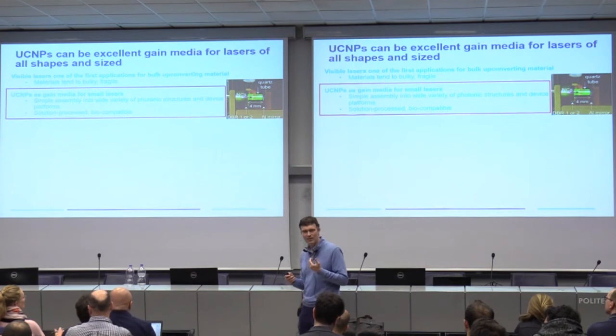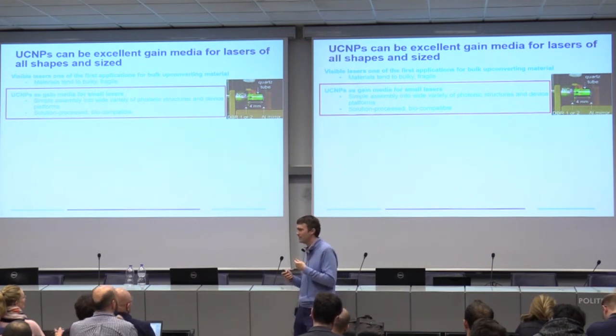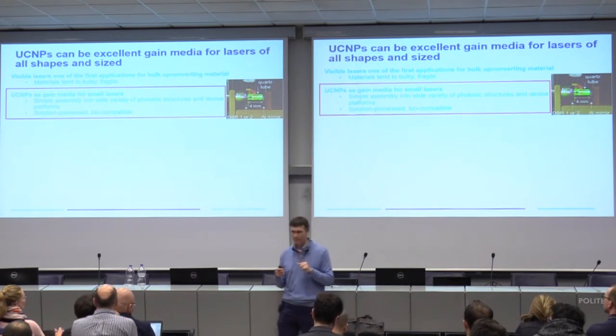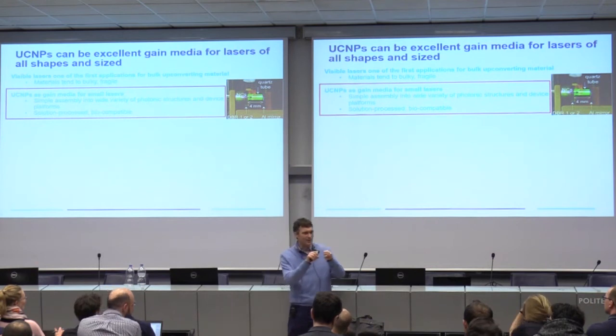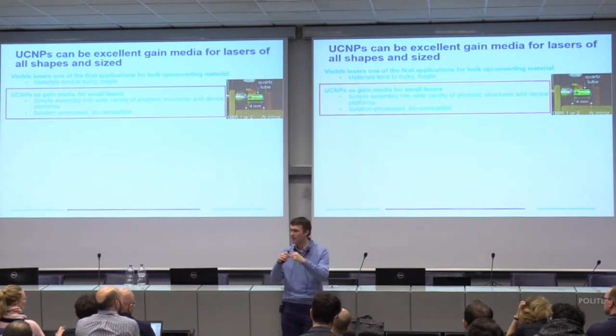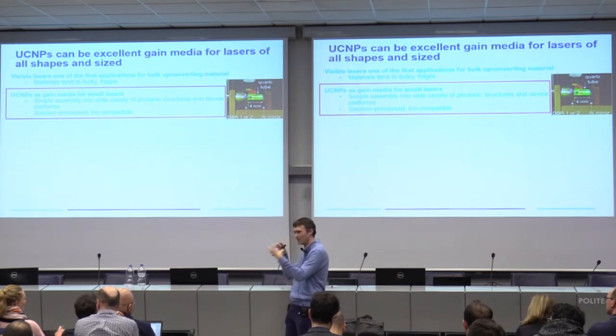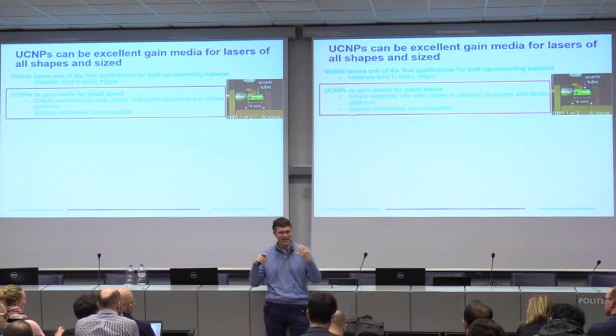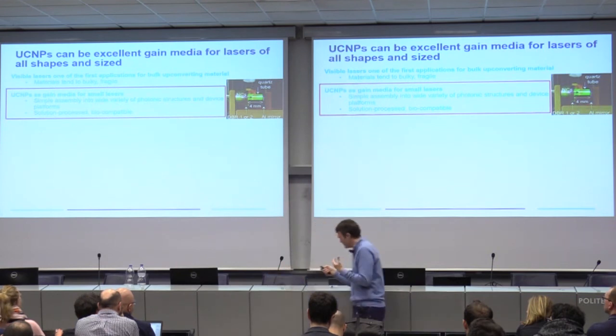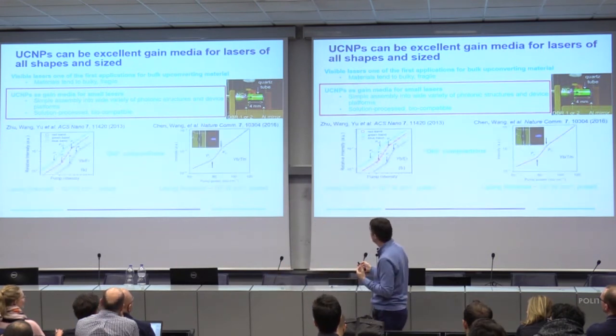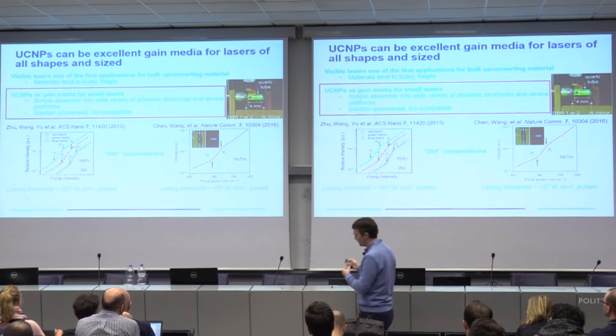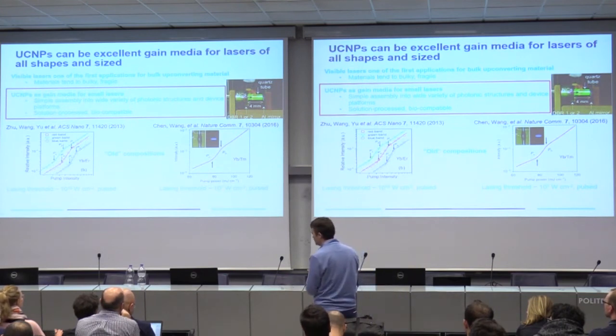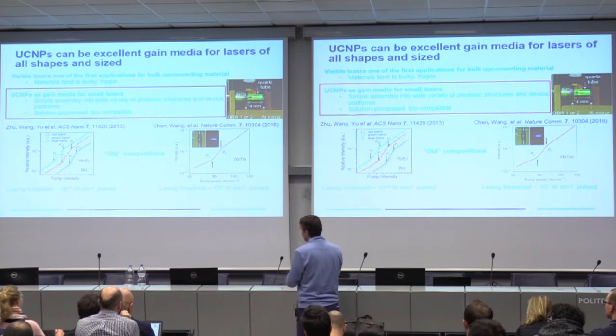But then you can start rethinking. Now we've got the same material, but in these perfectly tiny little nanoparticles, these little packets of gain material. Maybe there's an advantage here. Now we don't have to just leave them in a crystal shape. We can coat them onto anything. And so people started doing that. This is some great work from a guy named Feng Wang, who's in Singapore, I believe. And so he did start making lasers out of these materials.